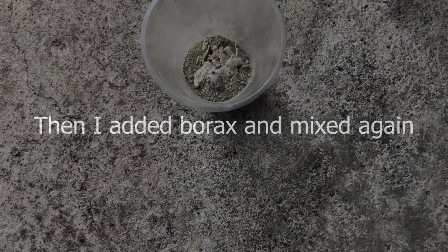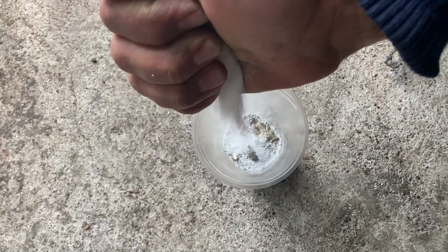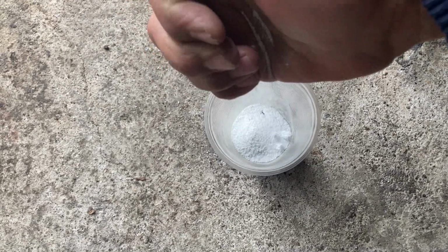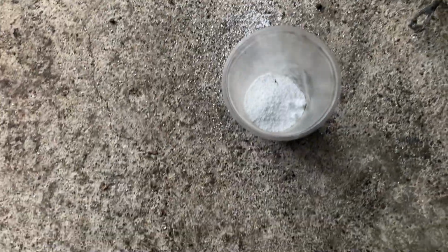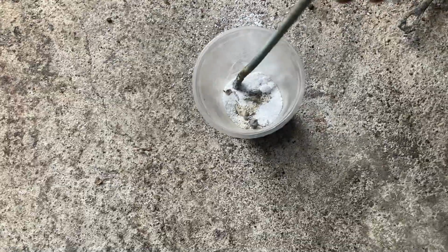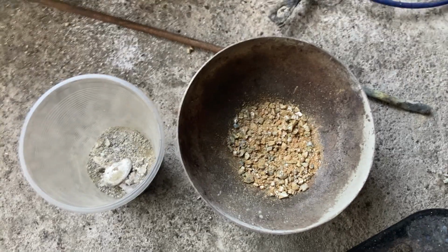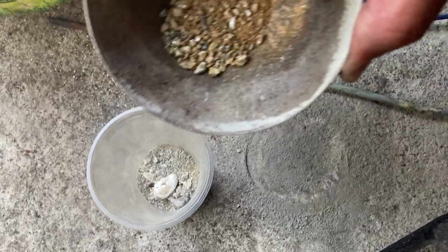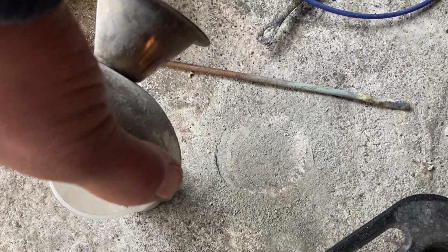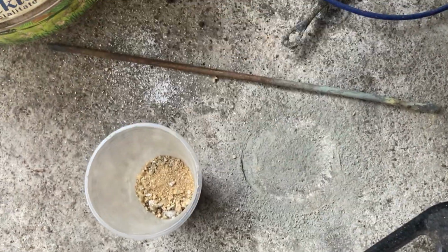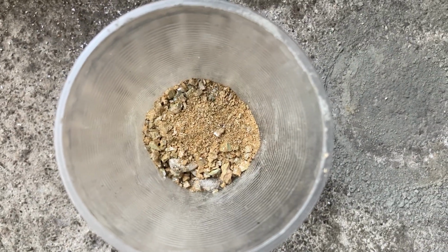Then I added borax and mixed again. About 60 grams of litharge were also added and mixed with the rest of the charge. Finally, the charge was covered with sodium hydroxide. After preheating the scorification dish, I placed the charge and added about 200 grams of lead metal.